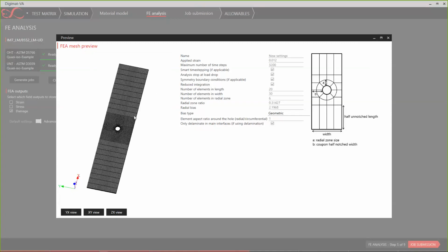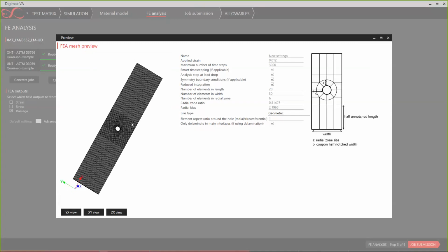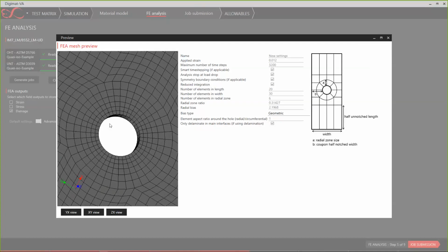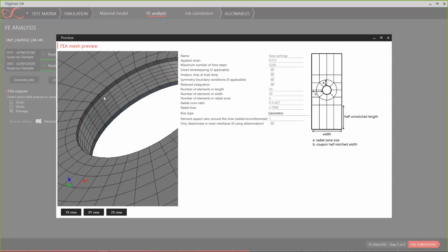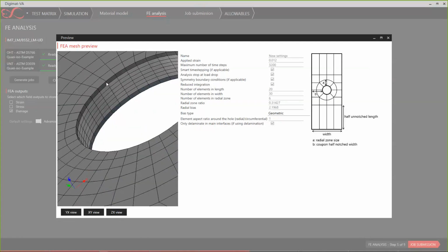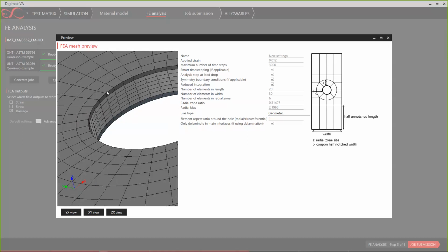And we can zoom a little bit around the hole. We see here three colors through the mesh. This means that we actually have three different materials. This is due to the in situ strength of the composite. So here, because of the symmetry, this one because it's an external ply, and those ones it's nothing special. They are just inside the laminate.